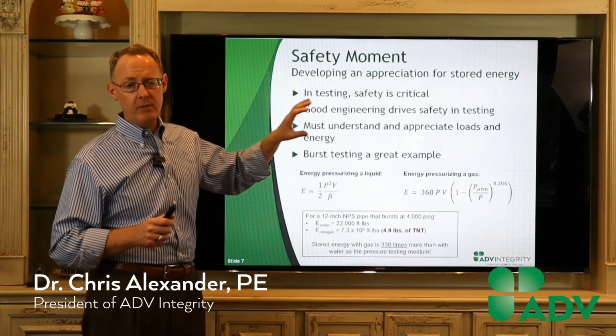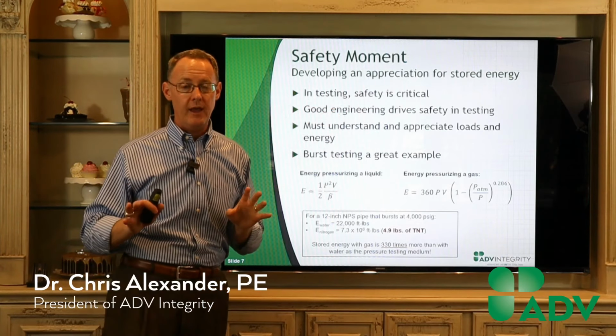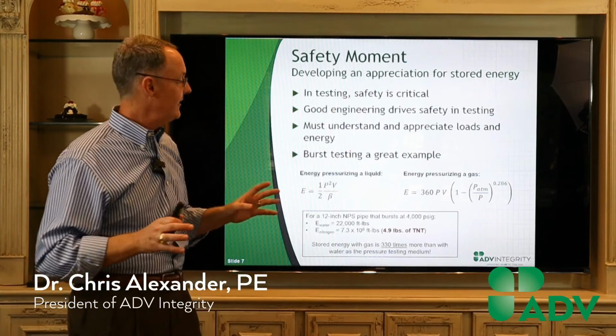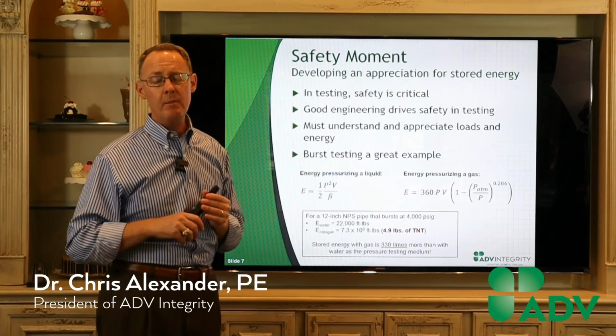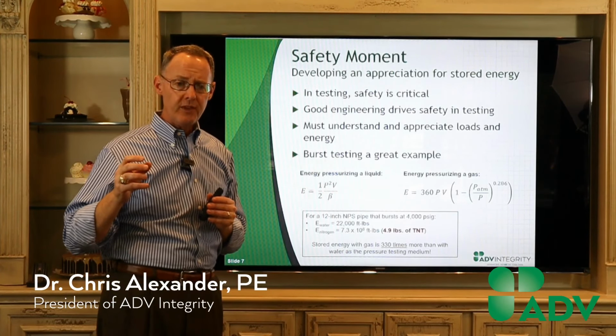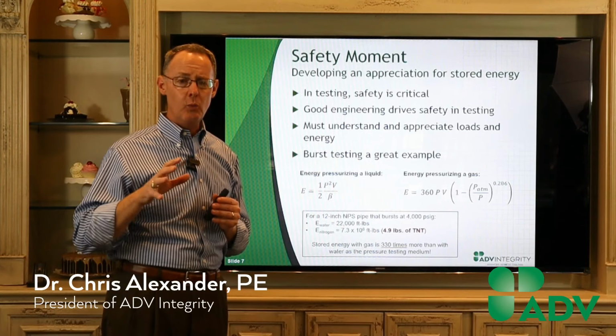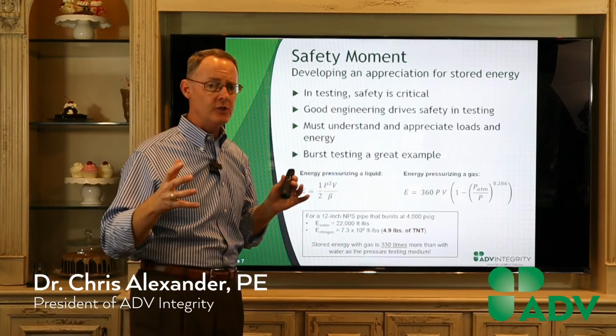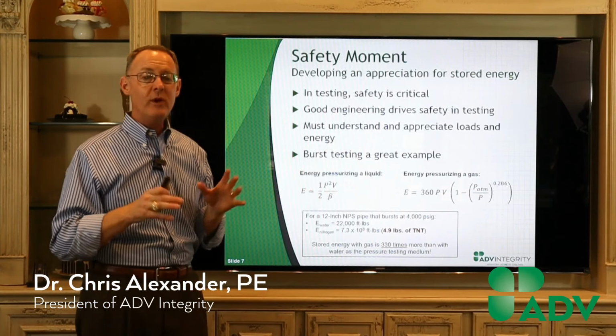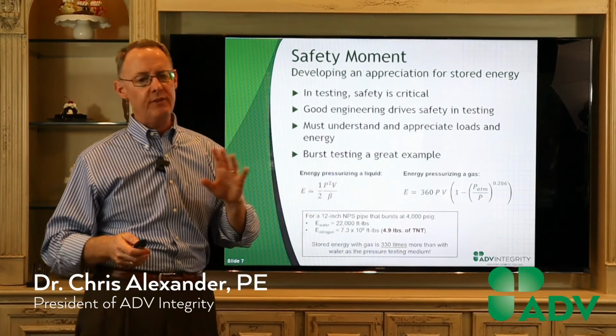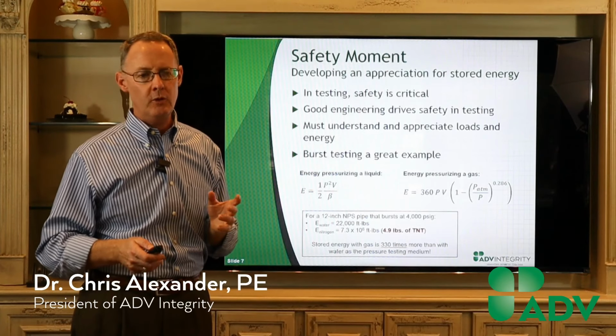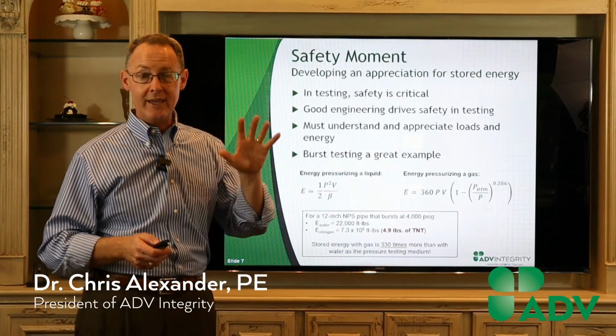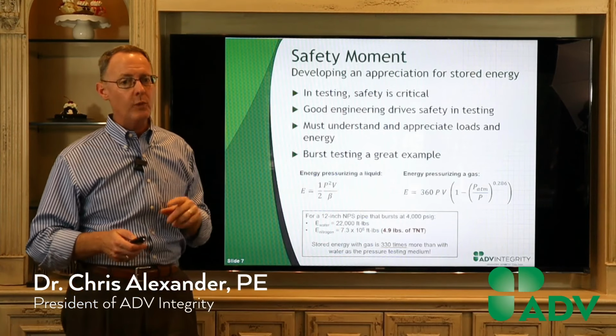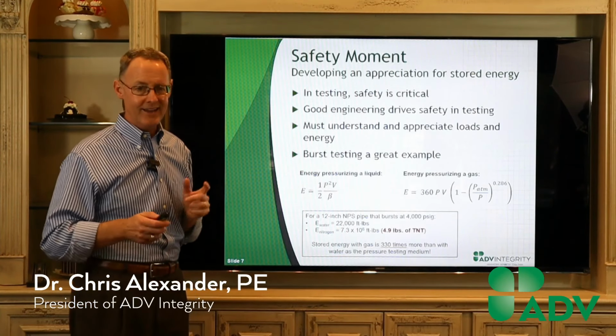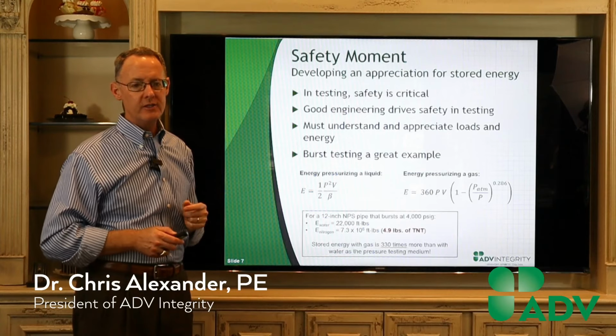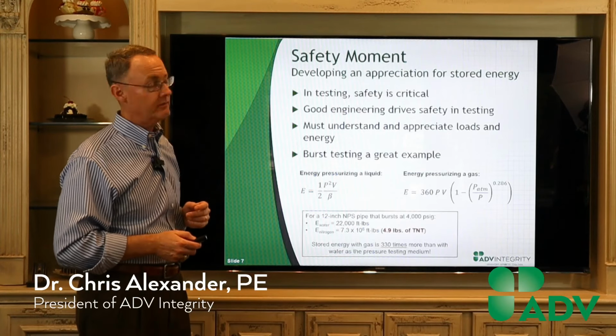Now, the reason I mention this, there's 2 things. Number one, you've learned something today. My guess is most of you have not seen these equations, and if you have, it's been a long time. But the other reason is that we think a lot about safety. And so before we do a test, we make sure the energy levels that we're going to be testing with, that we can safely do those. And I'm happy to report for the vast majority of pipeline testing that we do, we've got the facilities to do that. We did do a gas test about 1.5 years ago, and we did it at another facility. Everything went great. But in our shop, we're not going to be doing burst tests with gas.